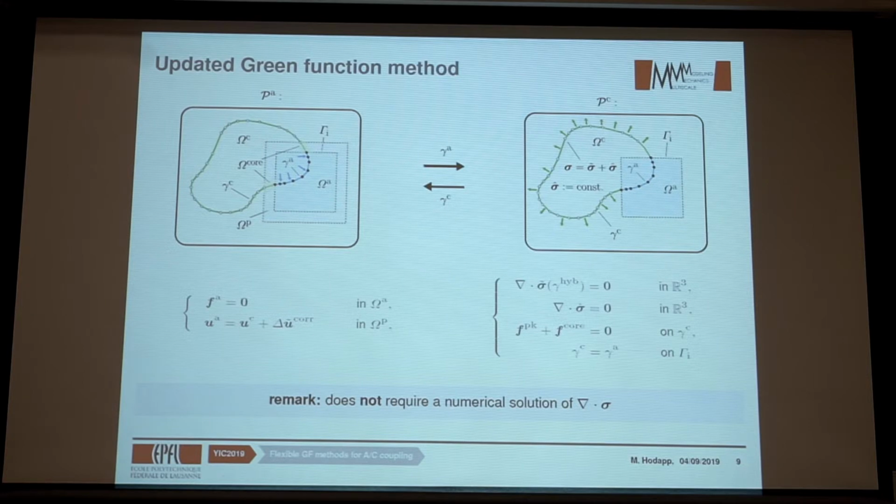In the continuum problem, what we do is we take this dislocation line and we connect it to our continuum dislocation line. To complete the dislocation network, we again compute the Green function of our entire dislocation network, and we evolve the dislocation in the continuum domain. And then we iterate between the two problems until we converge.